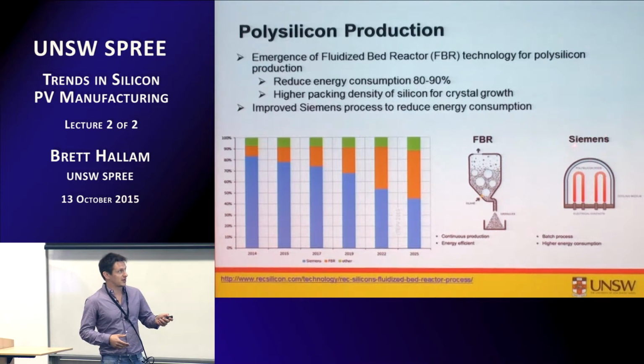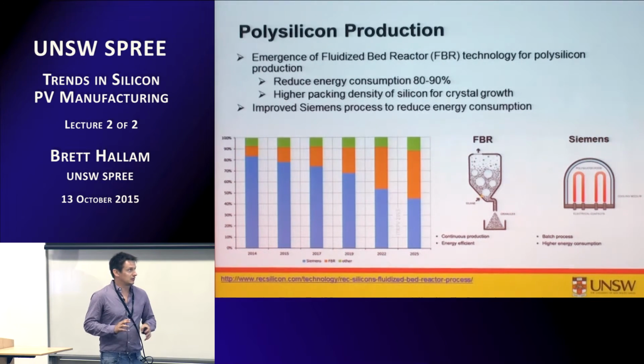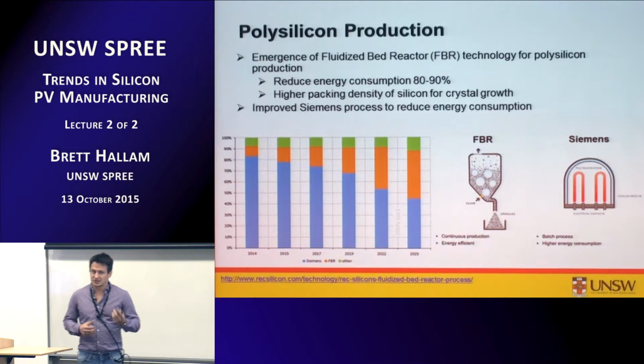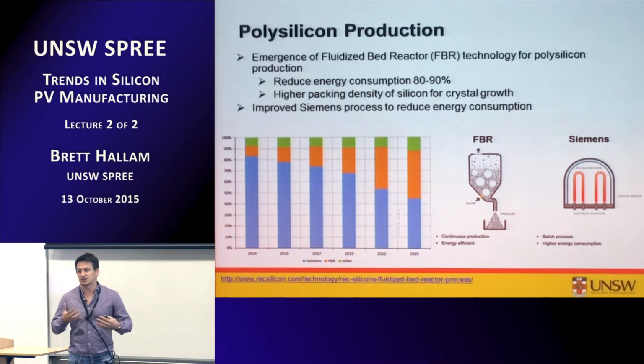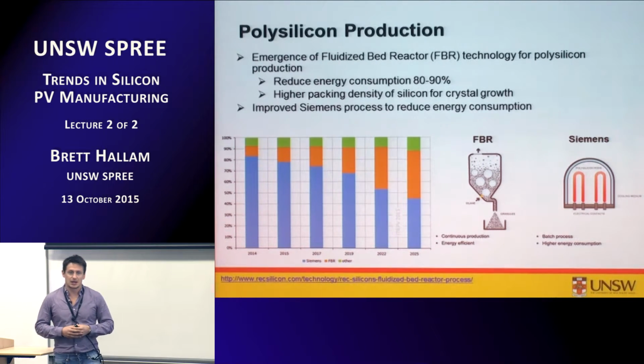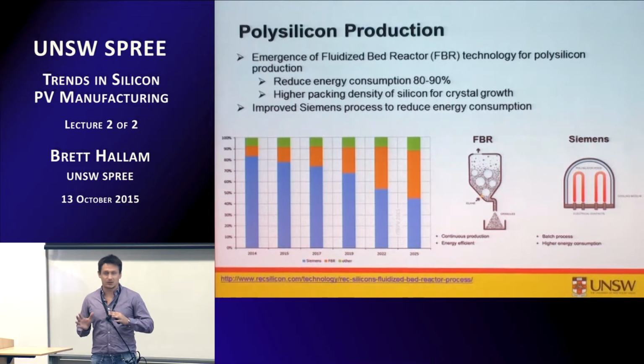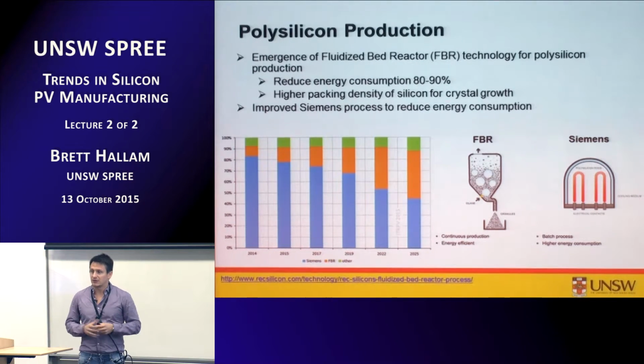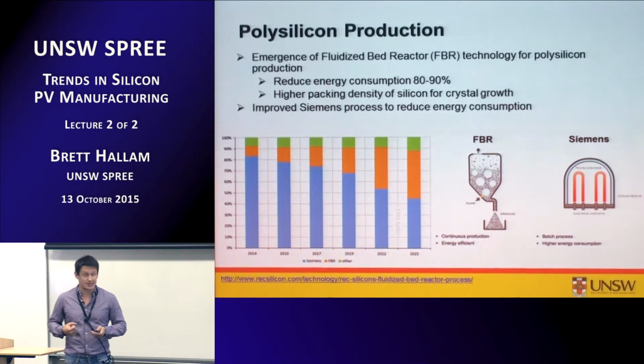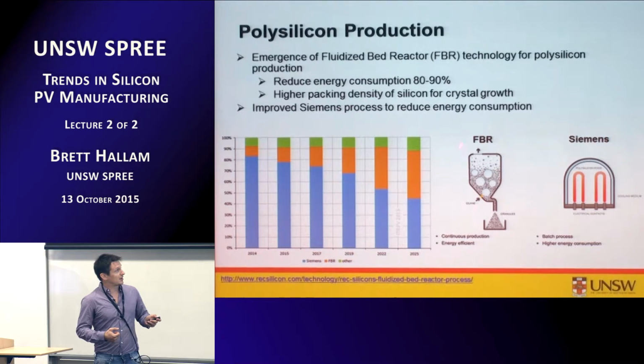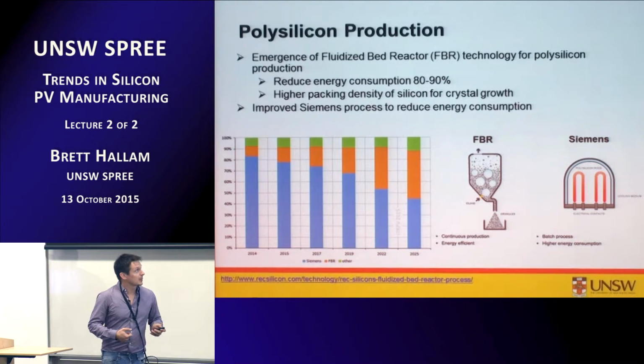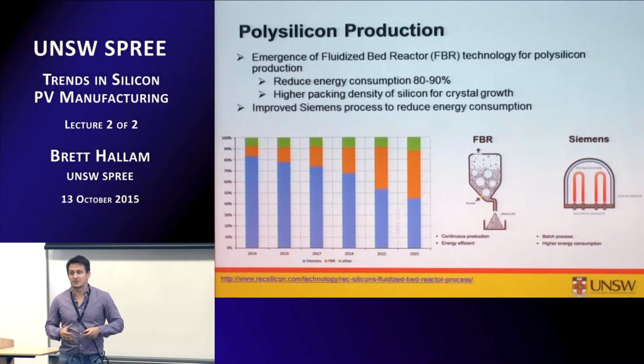So this is very, very energy intensive. From memory, it was like 110 kilowatt hours per kilogram of silicon, whatever. There have been some improvements to some of the later generation of the Siemens reactors to reduce, I think by maybe a factor of 4, the energy consumption in this process, but nonetheless it's still very, very energy intensive. Whereas with the FBR technology, it's looking at 80 to 90% reduction in energy, and it's also in line.